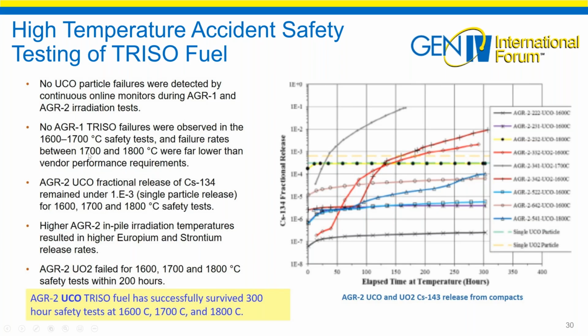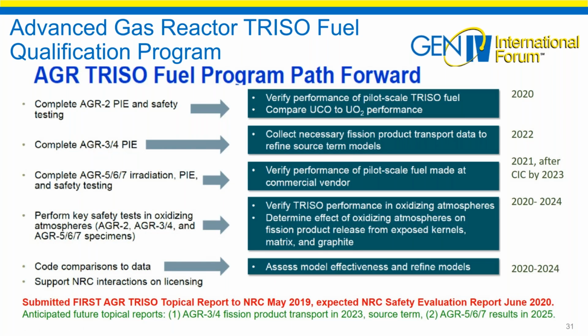So there's margin there. And there were a few failure rates when we pushed the temperatures up to 1800 C, but it was much lower than what the fuel vendor or the reactor vendor would need for the performance requirement during the accident. Remember that we needed to have that 10 to the minus 4. Our fractional release of cesium remained under 10 to the minus 3 for single particle releases here for our safety test. We did see some europium and higher strontium releases, but the UO2 fuel failed at the temperatures easily within 200 hours. So the UCO fuel was successfully tested. UO2 fuel would fail. Where are we today?